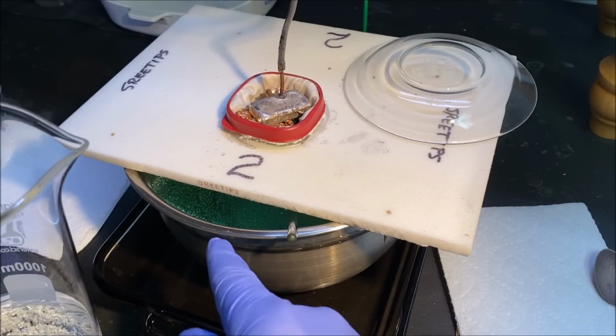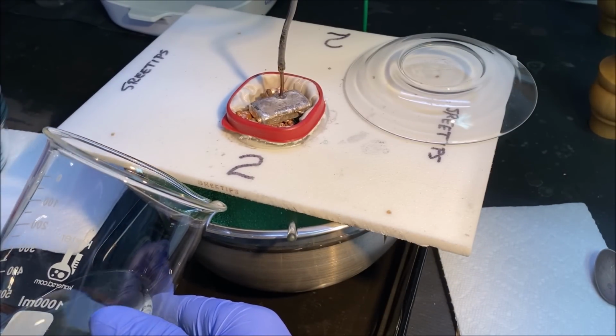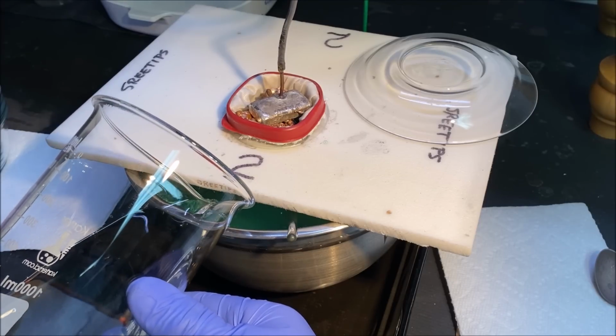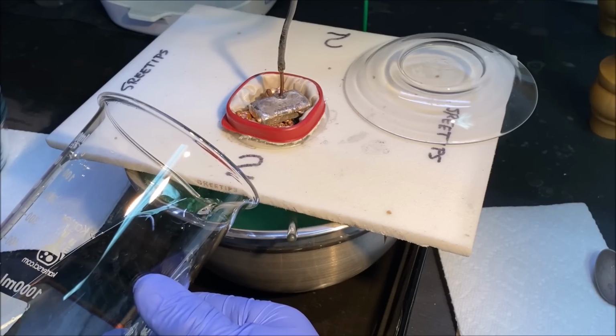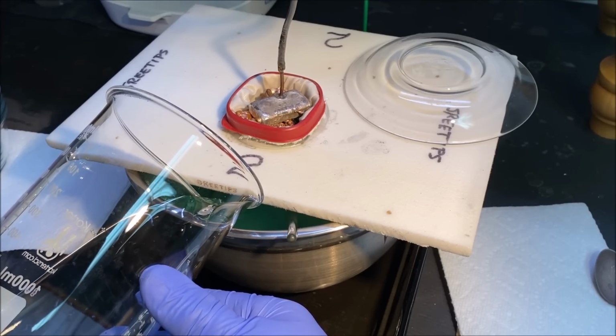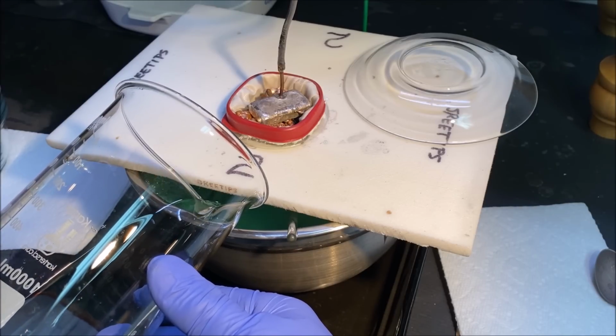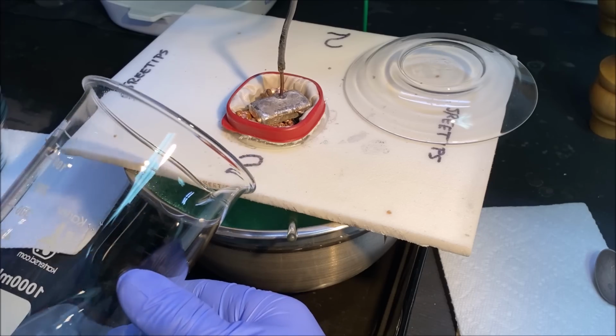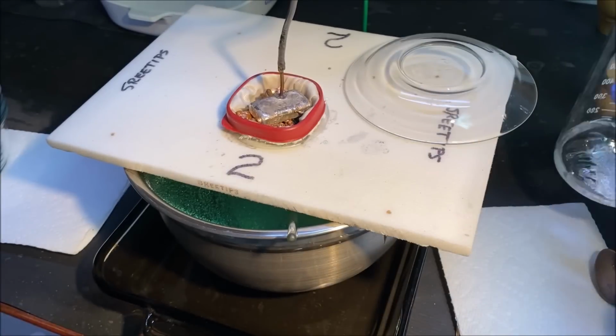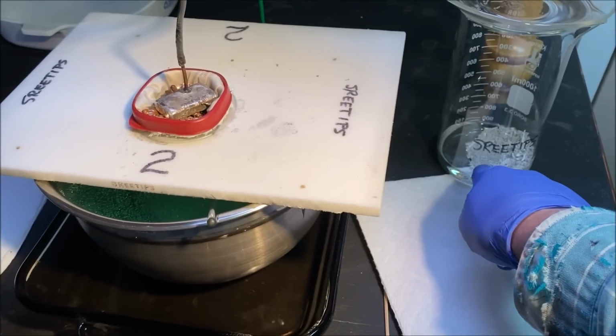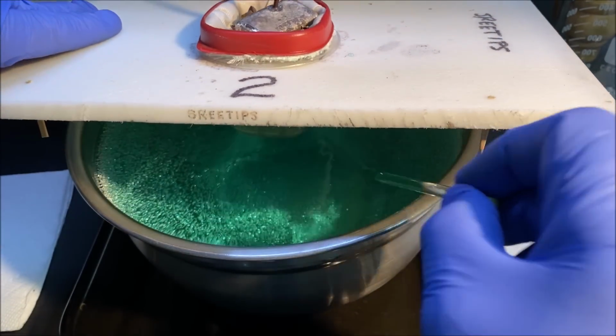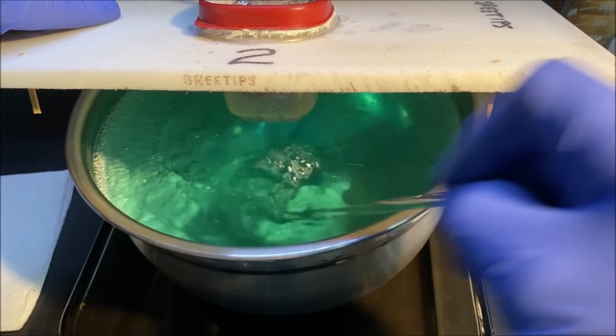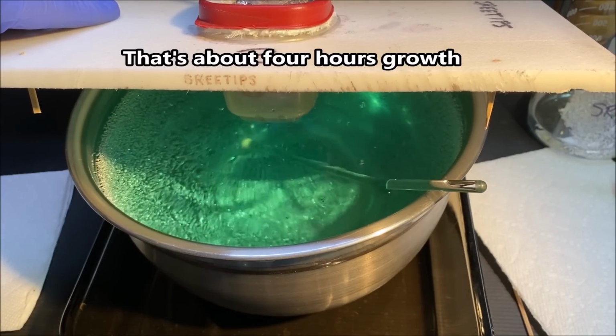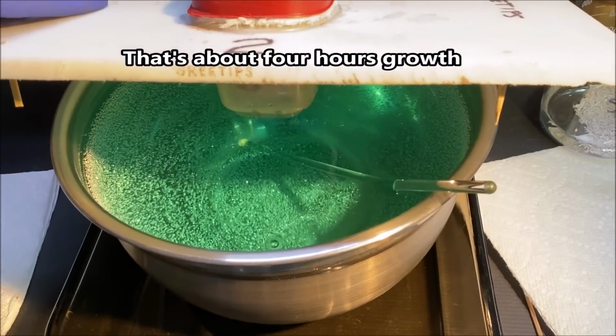You can see down inside the cell there that the electrolyte in there has already turned a nice blue color. So now we're going to add some of this fresh electrolyte. And that's probably 100 grams of silver that I just added in there. I'll dissolve the rest of that and use it to replenish electrolyte as this cell progresses. Stir this up real good. You see the blue color forming in there from the copper. Man, it just looks superior, man. Look at that.